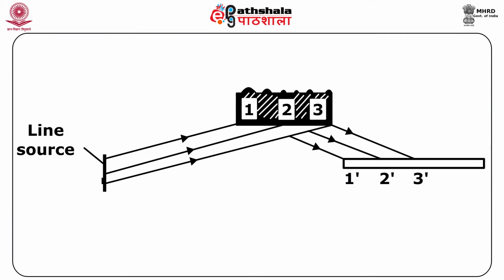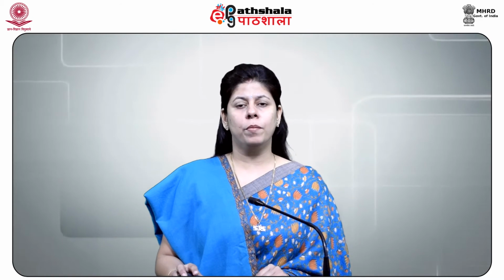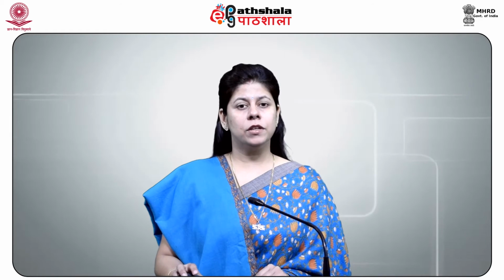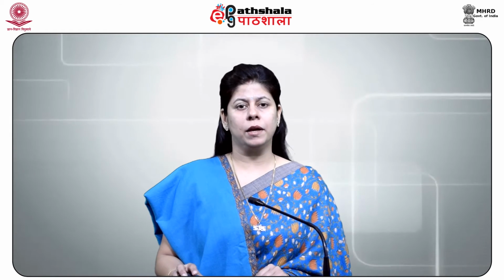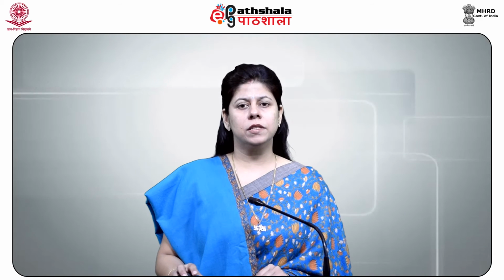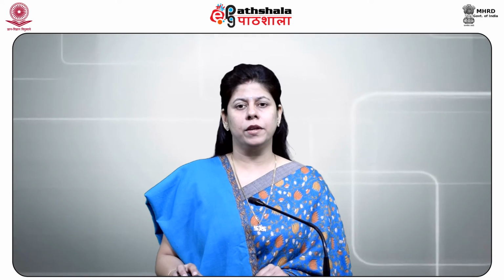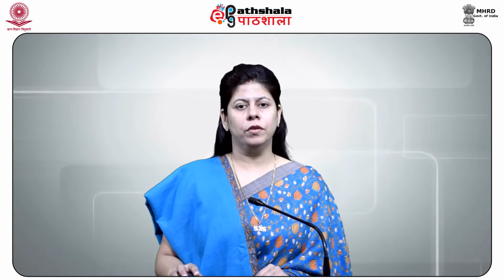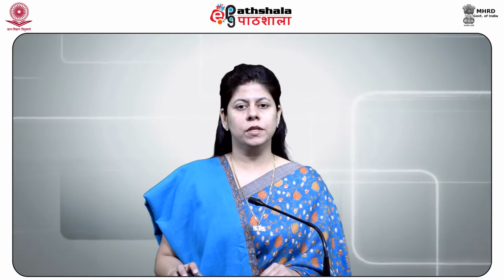One much used method of X-ray diffraction topography is known as Berg-Barrett method. The experimental arrangement is shown in the figure. The crystal is placed so as to reflect the X-rays at the Bragg angle for some plane. Geometric resolutions of about 1 micrometer can be achieved and single dislocations can be resolved. The dissimilarity on the film is owing to variation of the reflecting power due to imperfections in the crystal.